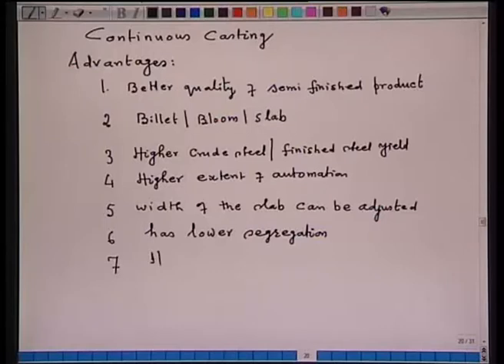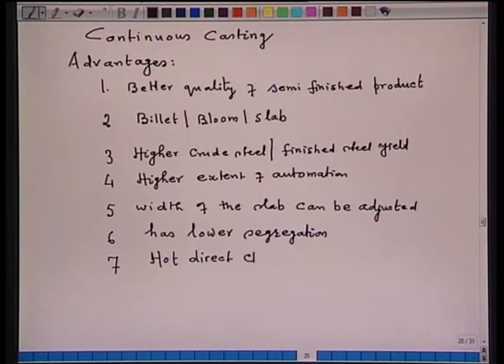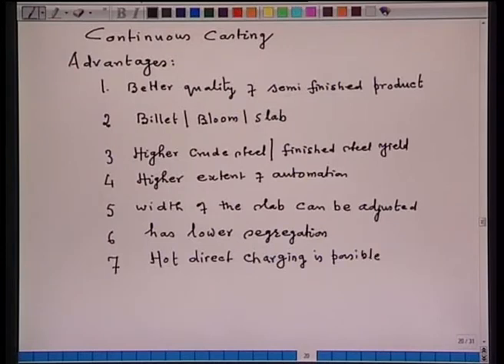Another very important benefit is that hot direct charging of the semi-finished product into the rolling mill is possible and is being practiced. The semi-finished product after continuous casting has a very high temperature of the order of 600–700°C, so that much energy is saved while reheating the billet for rolling purposes. This is a very important advantage in terms of energy conservation.